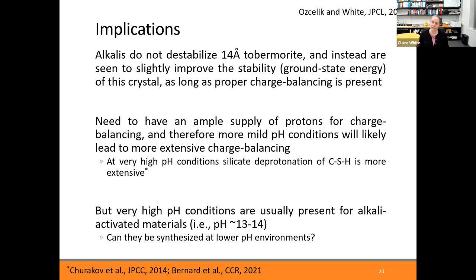What we're going to look at now is what happens if we are not just replacing one calcium with a sodium and a proton, but two or more calciums in the system. Because in the N-A-S-H gel that forms, there are going to be different amounts of sodium incorporated into the gel depending on how much sodium is in the vicinity when the gel is forming. That's an assumption we have: if you have a low amount of sodium when the gel is forming, you only get a little bit of sodium ending up in the structure. Whereas if you have a much higher concentration of sodium during the formation of the gels, then it's more likely that a lot more sodium is going to end up in the phase, which could affect the performance of the gel.